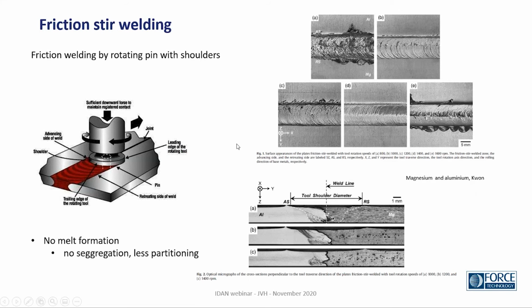I also mentioned friction stir, which is a method in use for aluminium, to join aluminium parts. It's friction because you have this rotating pin which rubs the material together. You have to imagine that the pin is going down into the metal, and by the friction between the tool shoulder and the pin, you rub the material together in a friction weld. There's no melting, so we don't get the solidification problems and the intermetallics forming in a melt. And we can combine the materials and have cross sections like illustrated down here.